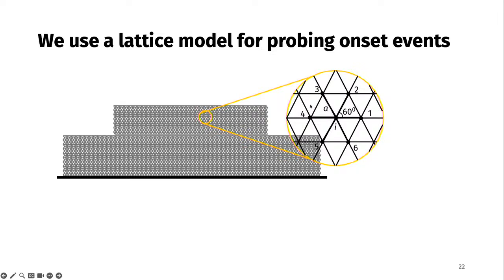Each node sits on a triangular lattice, and you have this type of connectivity, 60-degree bonds, and there is a normal stiffness and a tangential stiffness between each pair of nodes. You need both of these because you have to fit two elastic constants, the Young's modulus and the Poisson ratio. If you had just one spring, then the Poisson ratio would be fixed for a given Young's modulus and a given lattice orientation. Now we can fix both independently by changing these two parameters.